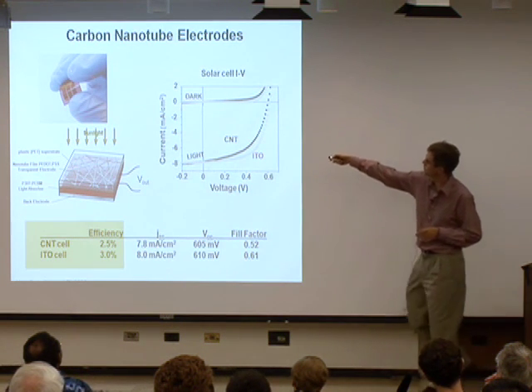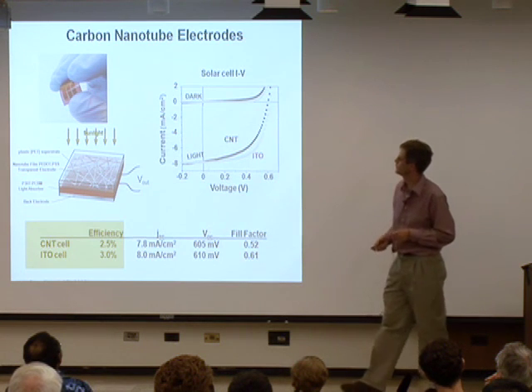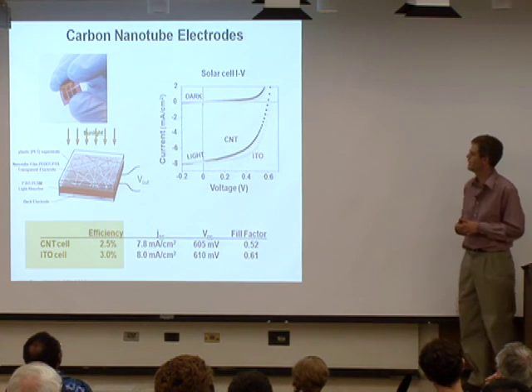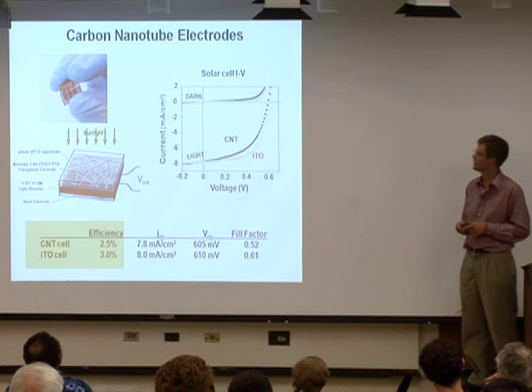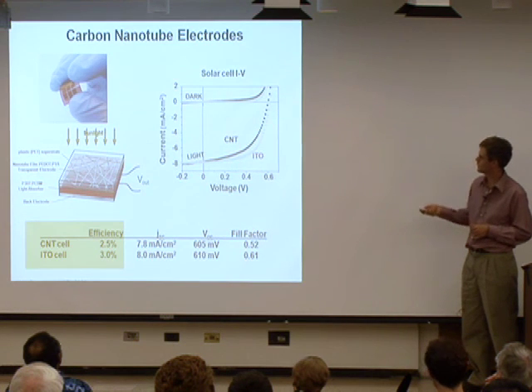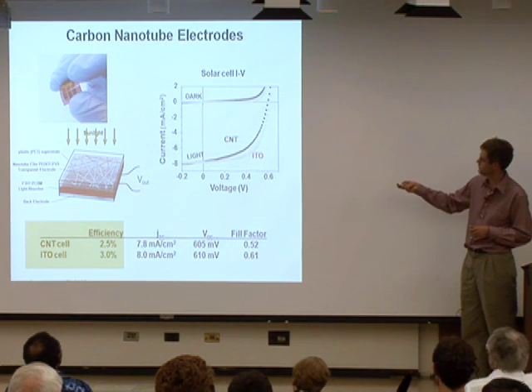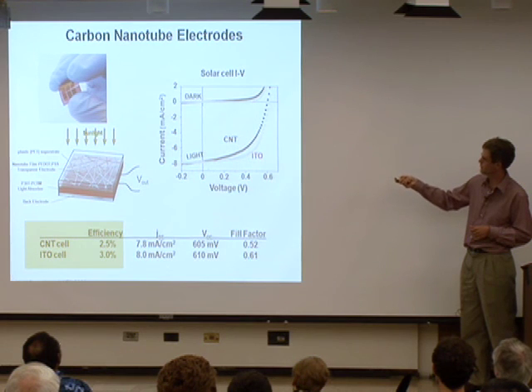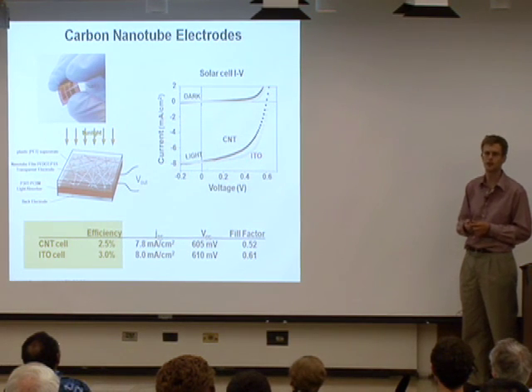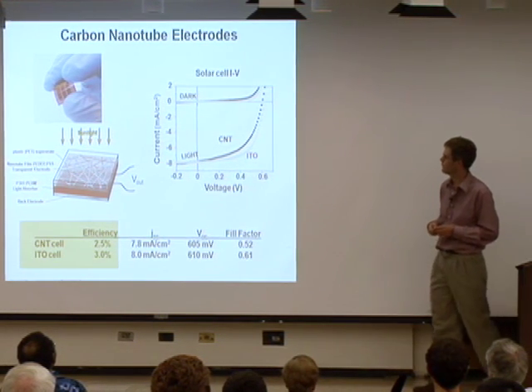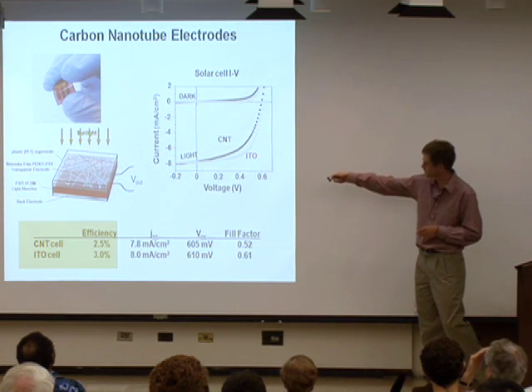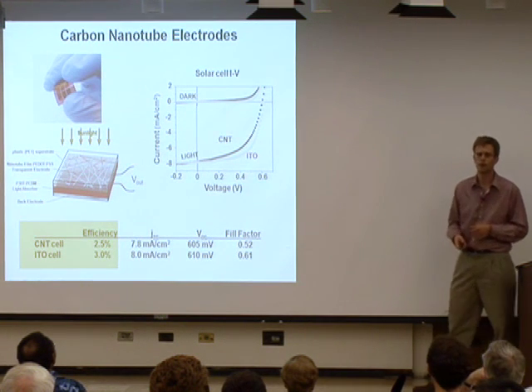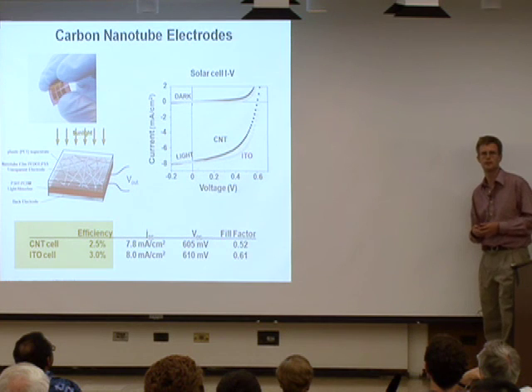So here you see a flexible solar cell that we've made in my lab using the nanotubes. Right now, the cells with nanotube electrodes are almost as good as those with ITO. They're only about 15% worse. And so if we could improve these a little bit, we would possibly be able to replace ITO.